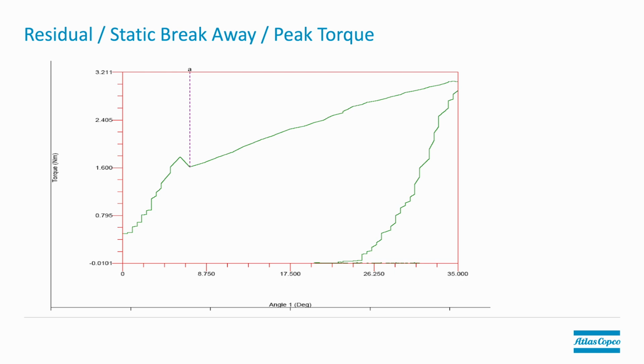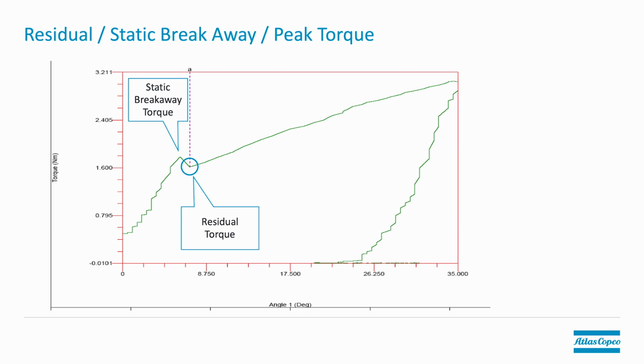So here's a zoomed in picture, a different application, but a good actual trace of an actual residual torque value. We have our static breakaway torque. This is the torque it takes to start it moving in the tightening direction. And then this point right here is what we call the residual torque. This is the best indication of the torque that's left in the joint, and it's the best indicator of what my dynamic torque was during the assembly. So the reason we're doing this process, this checking of the torque after it's been tightened, is to understand how much torque was applied in the original application. So during our tightening process, we use this as an audit to verify how good our tightening process was by checking the residual torque.